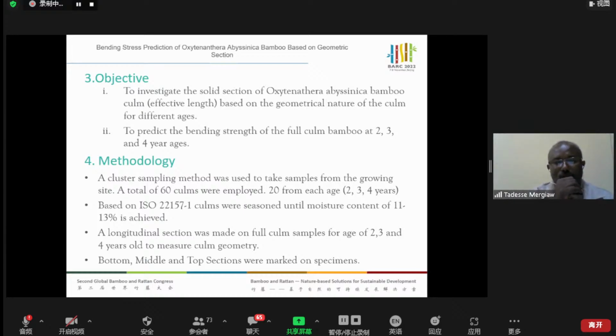So having these objectives, applying ISO 22157-1, a total of 60 culms were selected based on the cluster sampling method. They were dried naturally by vertically stacking in the laboratory of Bahir Dar University, Faculty of Civil Engineering Department, and kept until a moisture content of 11 to 13% was achieved.